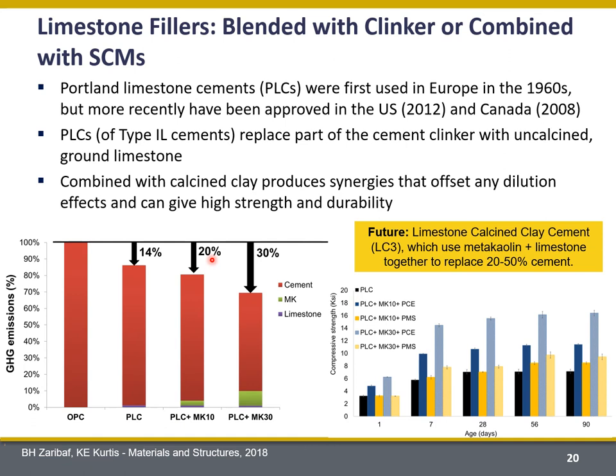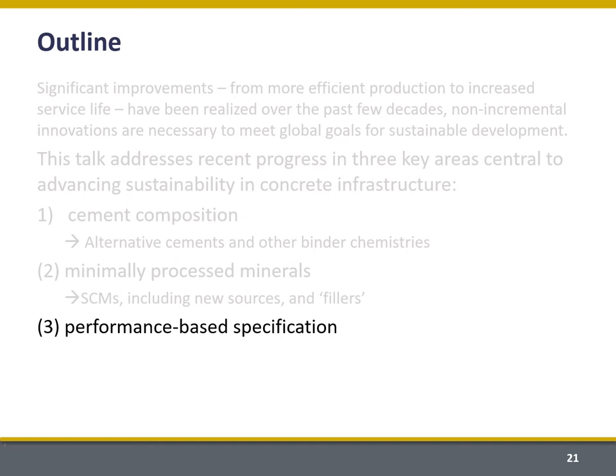You can see the accumulated combination of limestone cement with 10% metakaolin and also 30% metakaolin can create big savings in greenhouse gases. Comparing strength development, Portland limestone cement is very similar to Portland cement in terms of strength. If we use the right admixtures to disperse the clay as well, we can achieve significantly higher strengths with these limestone calcined clay — what are called LC3 cements. Together they can replace up to 50% of the cement. I really do think that's an important strategy for the future.